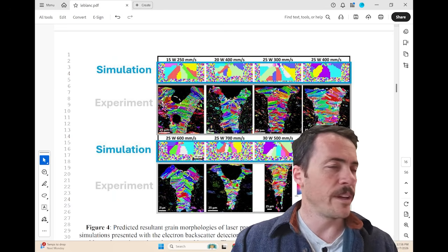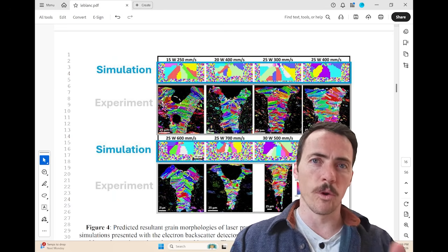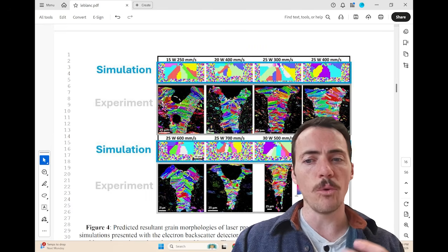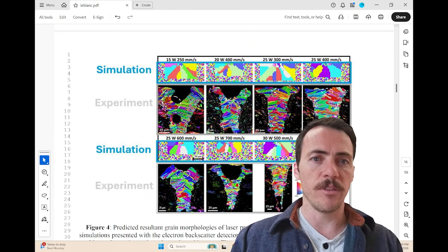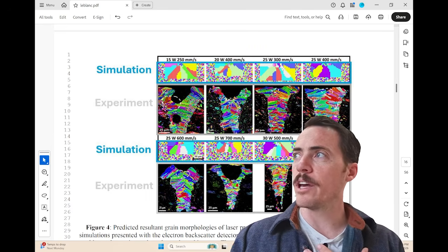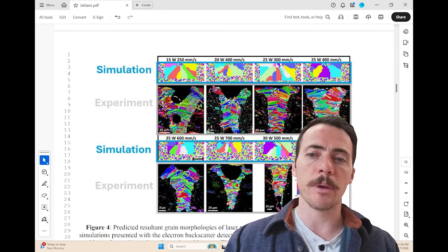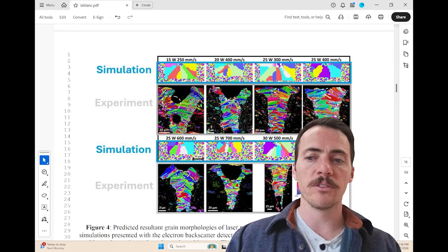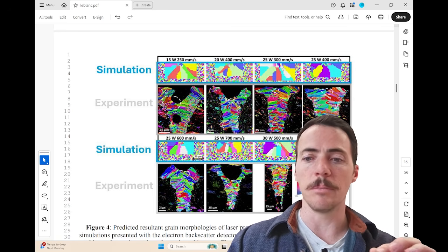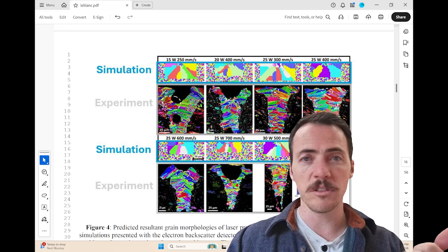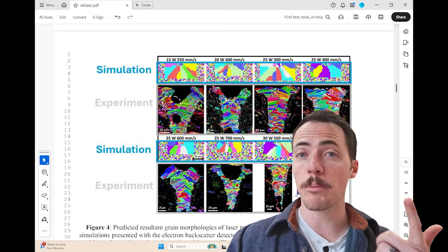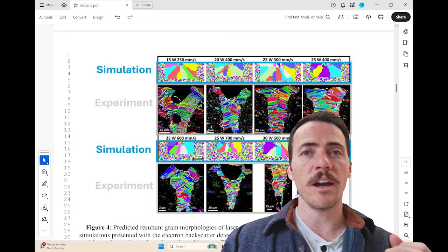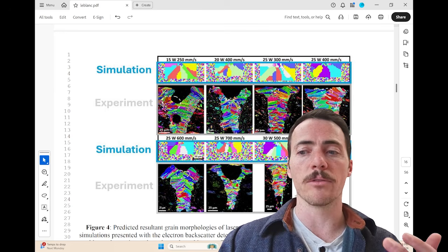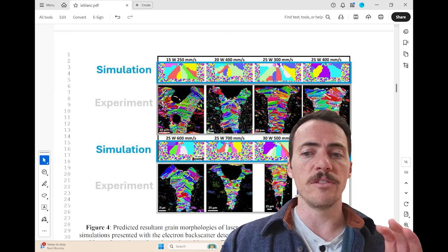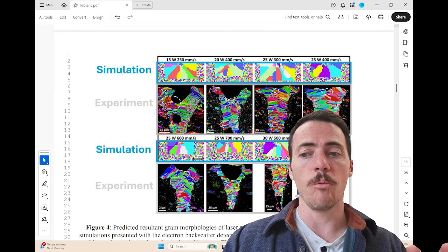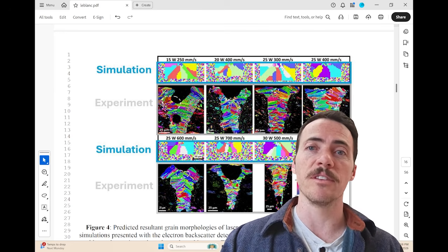And as usual, in IMMI, we're less interested in sort of one-off studies and more interested in new ideologies and frameworks. And this paper basically is telling me that, okay, the rules that we've derived for laser powder bed fusion, if they're made for metals, they can't just blindly be used for functional materials because you have new instability modes, you've got narrower processing windows, and you've got tighter coupling between your thermal and your microstructure behavior. So these physics-informed modeling pipelines, while they can work, we have to respect the differences.